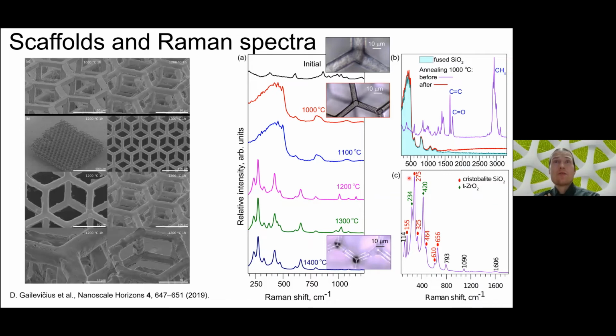Okay, so for the chemical analysis, yes, or material point of view, some scaffolds were made, as they are better for investigation since they provide larger volume and more material to study. So the initial pristine looks like this under the optical microscope, and if we heat at 1000 degrees, it shrinks, and at some point it turns kind of darkish, yes, like black or dark gray, perhaps due to attachment of carbon. But if you don't stop and are not afraid of this process and continue heating it, eventually it again becomes clear, and it was confirmed by both Raman spectra and XRD that there is no carbon left, and so the remaining material is polycrystalline and transparent, which is again important for microoptics and photonics applications.